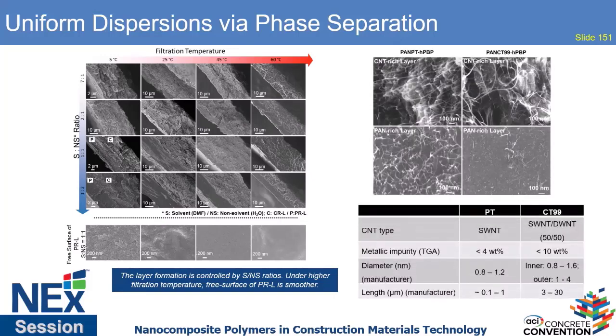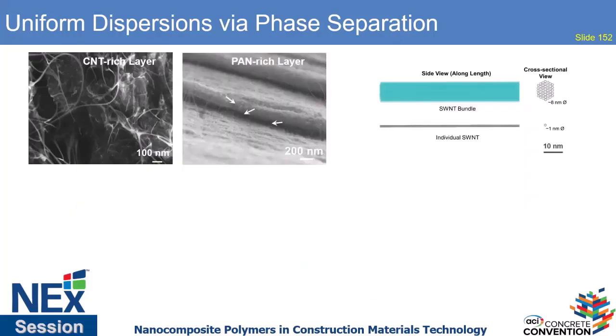So by understanding this, we've been doing this with different polymers, different molecular weight polymers, and different nanomaterials. We've been finding these essential relationships where a particular polymer, particular nanomaterial can give us these different types of arrangements, and we can use that as a means of learning how to disperse them better for the ultimate composite. And I will say the polymers that we're using in these cases are long chain polymers, usually linear polymers, because we spin fibers. So we need that type of polymer for a fiber.